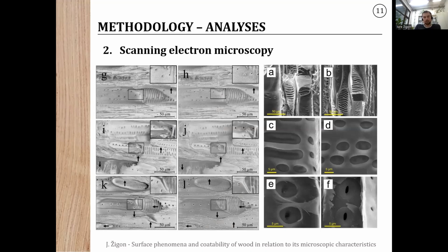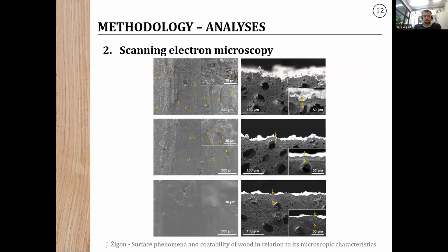Some examples of non-coated wood but exposed to artificial weathering are on the left side. So the same area, different spots before artificial weathering and after artificial weathering. So we were observing here what's happening with the wood tissue when it's exposed to light and humidity. And same on the right side, after doing some plasma treatment of wood, I was observing some changes in the microstructure of wood, of beech wood in this case.